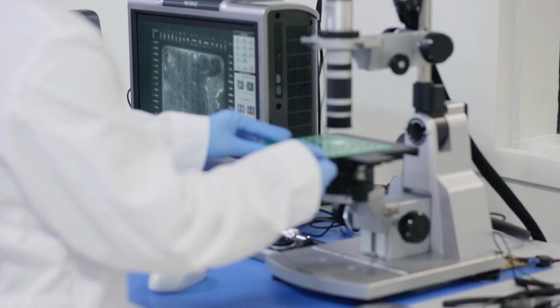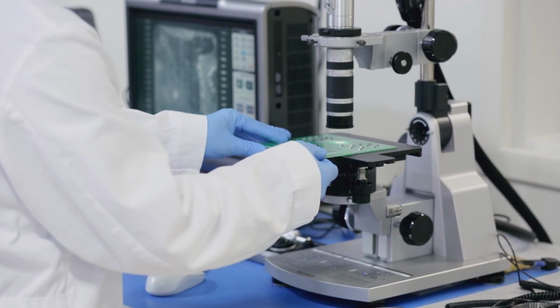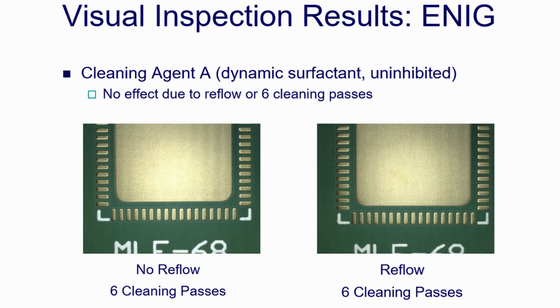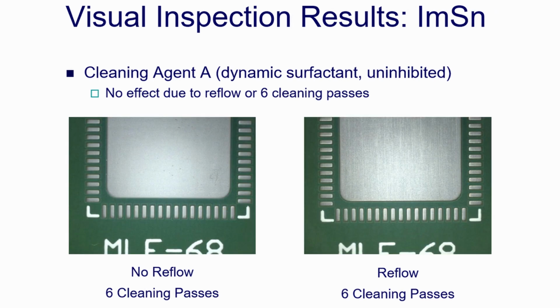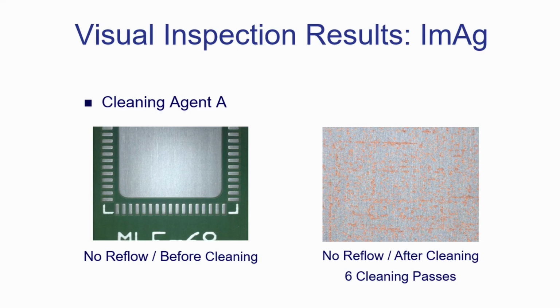After cleaning all the surface finishes with the various chemistries, various analytical tests were conducted. The first test conducted was visual inspection. During visual inspection under a microscope, it was found that all the cleaning agents were fully compatible with both the ENIG as well as the immersion tin platings. With the immersion silver, it was found that three of the chemistries were fully compatible, whereas the alkaline uninhibited surfactant-based chemistry started to remove some of the plating, especially after the six passes through the cleaning process.